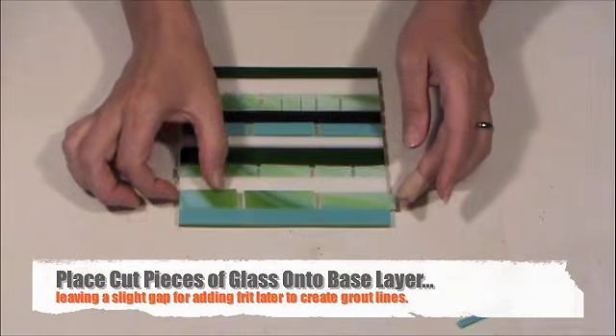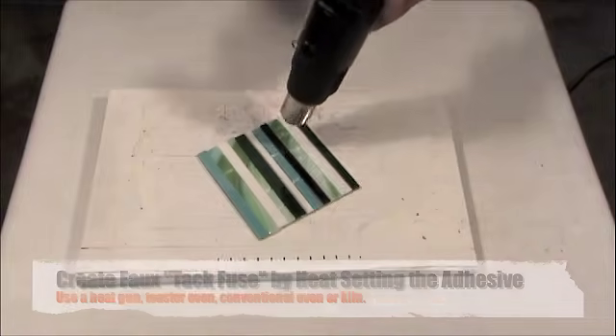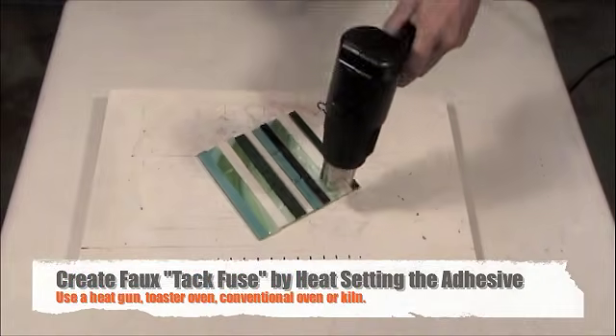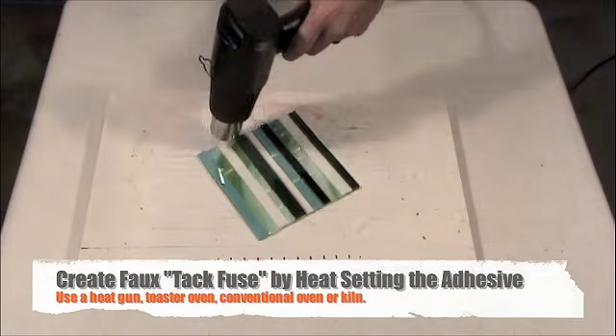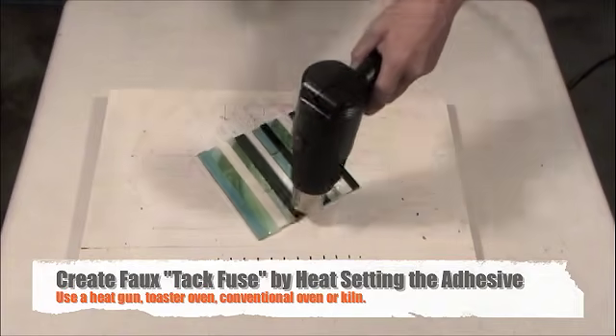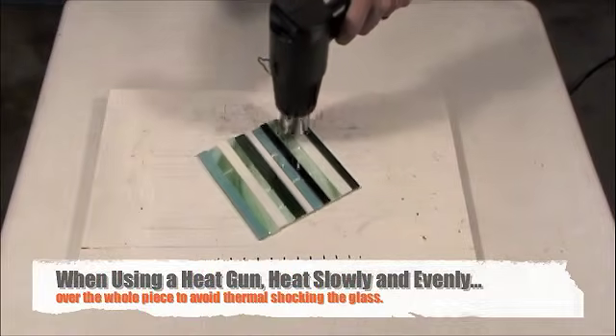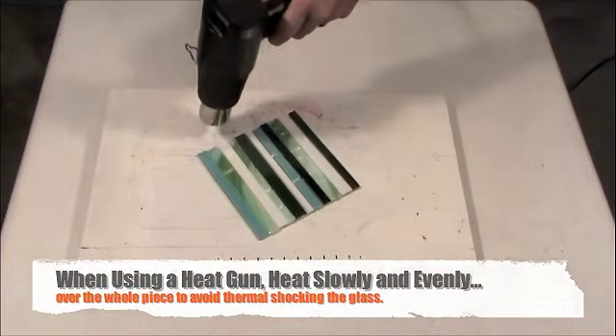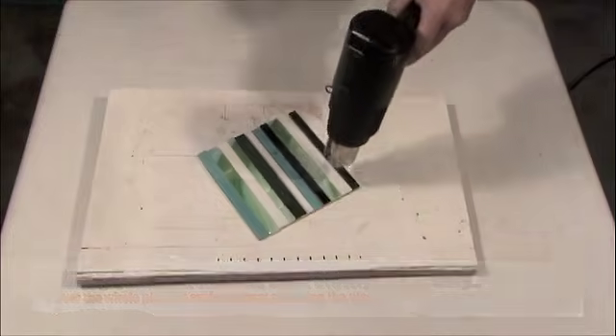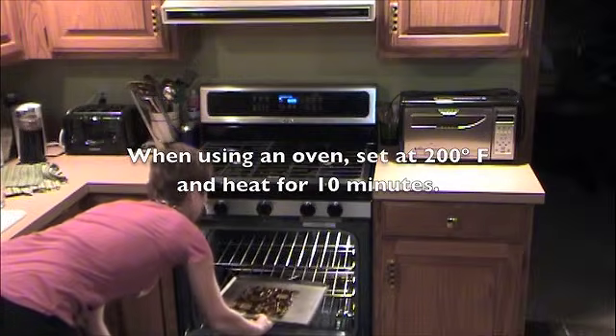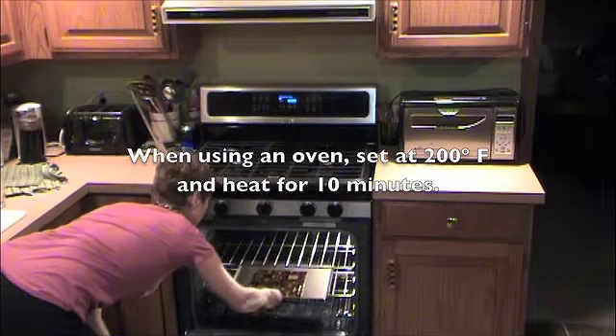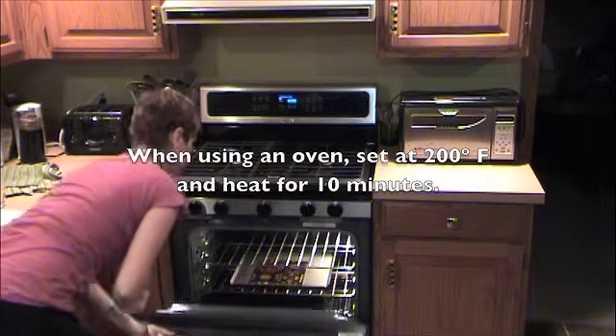To achieve a faux tack fuse, heat set the ThinFuse adhesive with a heat gun, oven, or kiln. The adhesive activates at 160 degrees Fahrenheit. If you're heating with a heat gun, make sure to heat the whole project slowly and evenly to avoid thermal shocking the glass. Alternatively, you can heat set the adhesive by placing the project in a toaster oven or conventional oven set to 200 degrees Fahrenheit for 10 minutes.